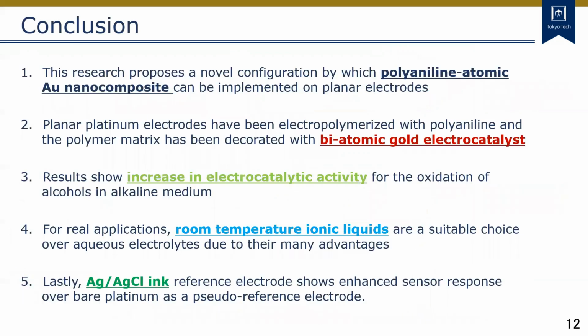Finally, the conclusions so far. This research proposes a novel configuration by which polyaniline-atomic Au nanocomposite can be implemented on planar electrodes. Planar platinum electrodes have been electropolymerized with polyaniline, and the polymer matrix has been decorated with biatomic gold electrocatalysts. Results show an increase in the electrocatalytic activity for the oxidation of alcohols in alkaline medium. For real applications, room temperature ionic liquids are a suitable choice over aqueous electrolytes due to their many advantages. Lastly, Ag/AgCl ink reference electrode shows enhanced sensor response over bare platinum as a pseudo-reference electrode.